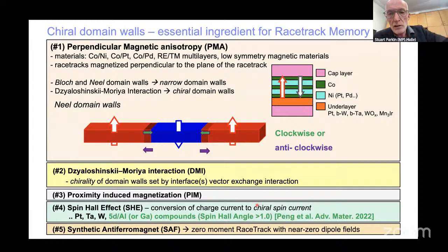So if I just go back to the basic ingredients for racetrack memory, I mentioned already perpendicular magnetic anisotropy. If you take very thin magnetic layers formed, let's say, from cobalt and nickel, the interfaces break symmetry and give rise to an interfacial anisotropy, and this can be increased by using layers like platinum with strong spin-orbit coupling. And this interfacial anisotropy is critically important to creating tiny, tiny magnetic domain walls. The very large anisotropy means the moments in the racetrack want to point up or down, as shown by these blue and red regions, and the domain walls in between are just a few nanometers wide.